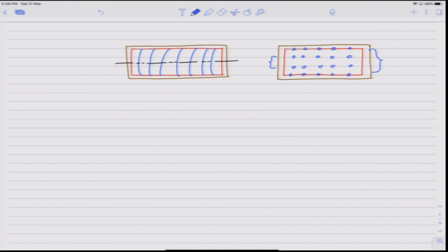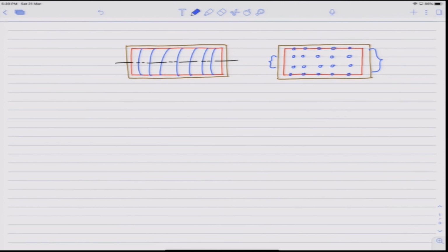That means the markers moved from the initial interface into the brass side. Since copper was diffusing from outside into the brass and the zinc was diffusing from brass into the copper, obviously this would have occurred because of the faster diffusion of zinc from inside out compared to the diffusion of copper from outside in.